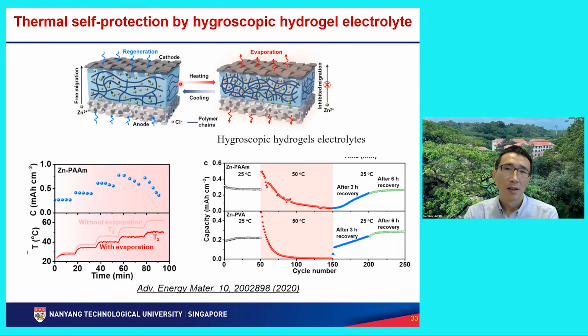Okay, that means the concentration of the ions inside becomes higher. If the concentration is too high, then they're not so mobile, not so movable. So the zinc ions inside will become less movable, and the battery will not work very well or not work at all. So it kind of protects the battery. Then when the temperature cools down, the water can be reabsorbed into the hydrogel, because the hydrogel can also capture water molecules into the cell, and then the ions start to swim again.